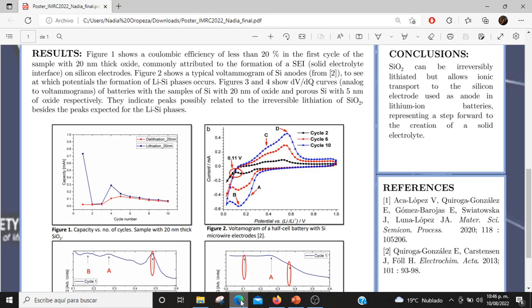The low efficiency has been commonly attributed to the formation of solid electrolyte interface on silicon electrodes. However, in the present cases, the silicon oxide layer is also participating in the process. Figure 2 shows a typical voltammogram of silicon anodes to see at which potentials the formation of lithium silicon phases occurs. To elucidate whether there is an effect of this layer, curves of the derivative of the voltage with respect to the capacity, which are analogous to voltammograms, were calculated from the cycling data.